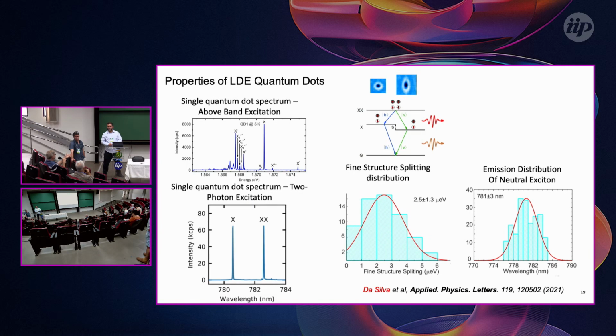You create less charge inside the dot, because I think when you excite above the conduction band, there are a lot of electrons coming inside the dot. Yes, probably. I have to confirm, because I'm confused: absorption of two photons in gallium arsenide is very small. If this is below the band gap, you have to have a pulsed laser with a very high intensity to get...